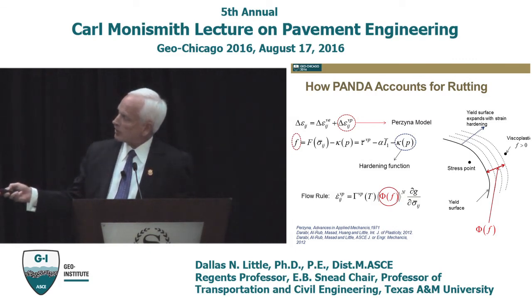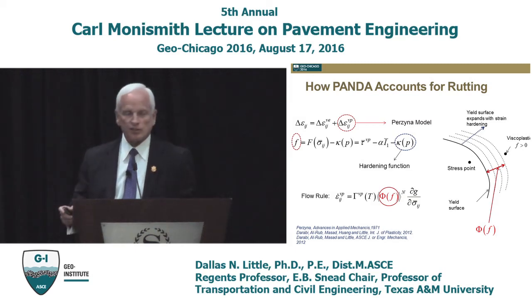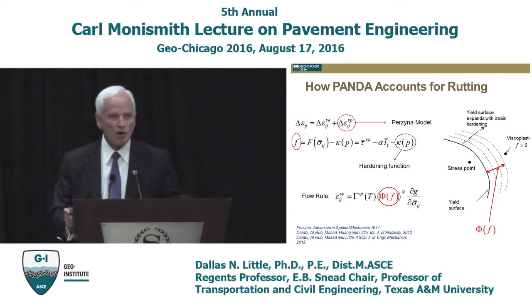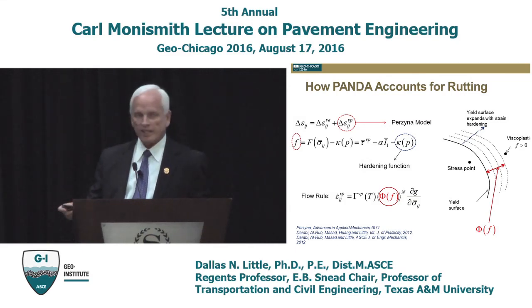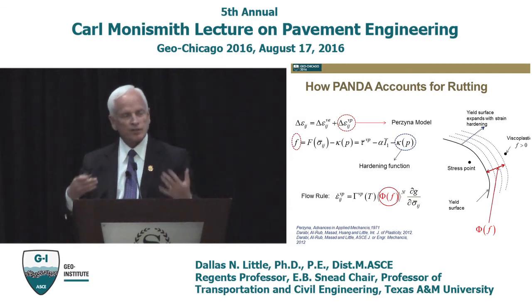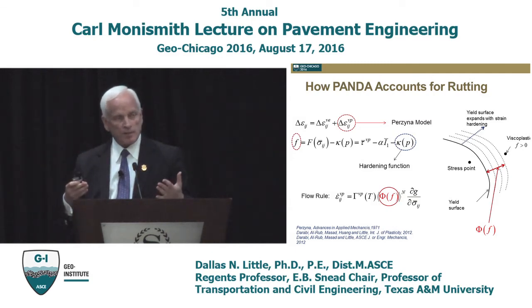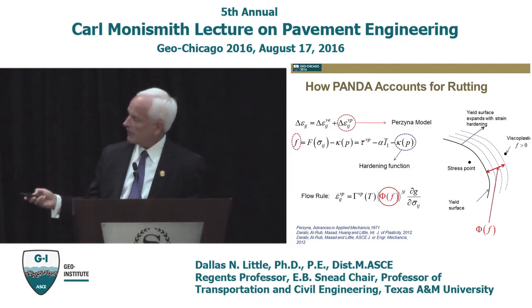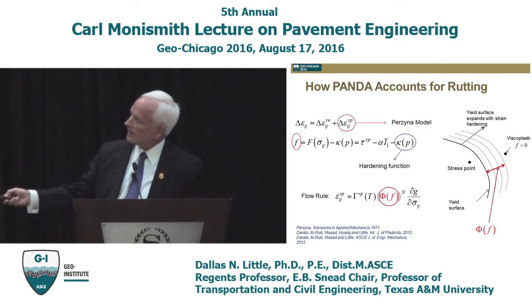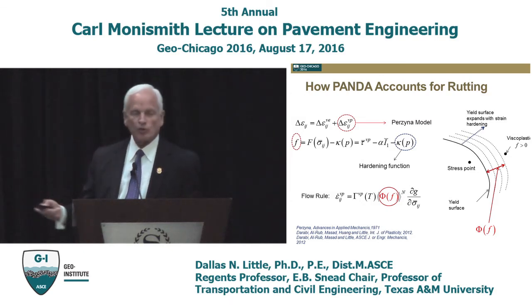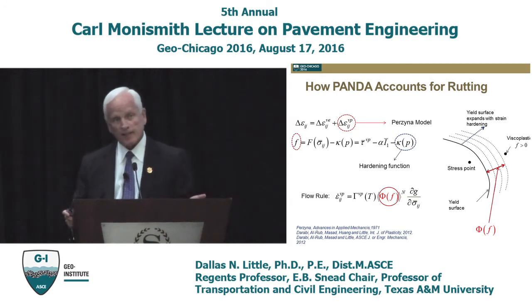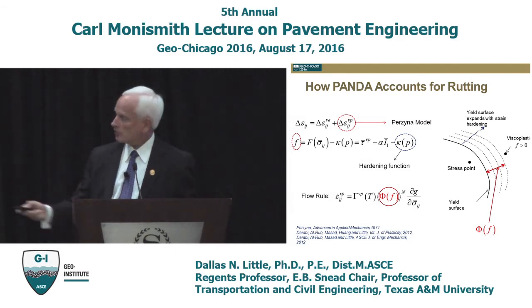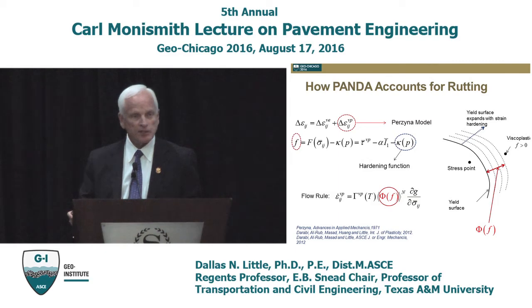So the viscoplastic component of strain is accounted for by a Perzyna type model. In 1971, Perzyna and his colleagues came up with a model that defines the rate of viscoplastic strain. And that function looks like this. It looks pretty complex, pretty hairy, but basically it starts off with an initial identifier of the rate of initial plastic deformation. That's the gamma superscript VP term.